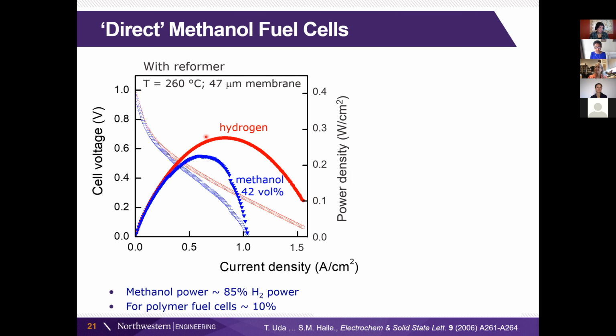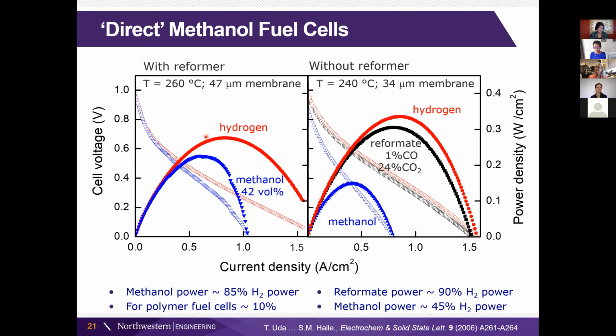And to prove to ourselves that the reformer was actually doing the work, we compare the performance of the cell without the reformer. So we've got no reformer. We're comparing hydrogen to methanol, and you can see there's a big drop. And the other thing is that we then just delivered perfect reformate, which has 1% CO, 24% CO2, and then balanced hydrogen. And of course, we humidify as well.